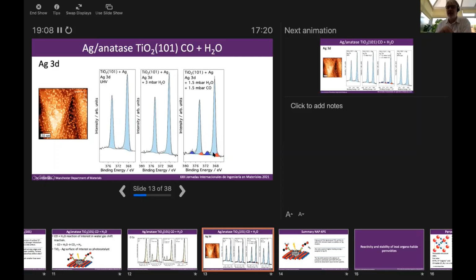Okay, so we can see there's some oxidation occurring of the silver, and we also see these second peaks. We're not entirely sure what these peaks are, but we believe they may be due to the presence of silver carbonyl species forming on the surface as the carbon monoxide comes down and attaches to the silver. So this is telling us that the water seems to interact with the titanium dioxide substrate, but the carbon monoxide is interacting almost exclusively with the silver.